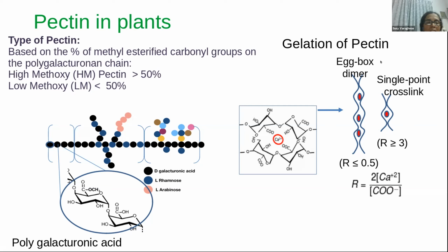So what is of interest to us in this molecule is this polygalacturonic acid group that is shown here, which, in the presence of calcium, the carboxylic acid groups here can go into a physical network and form what are known as egg box dimers. So these two parallel polysaccharide chains are shown here as the curled chain, and the red dots are the calcium that is nesting inside these chains. So when the calcium concentration, given as R here, is low, it forms this kind of dimers, or when the calcium cross-linking ratio is high, it can form either a single point cross-link or form networks of this.